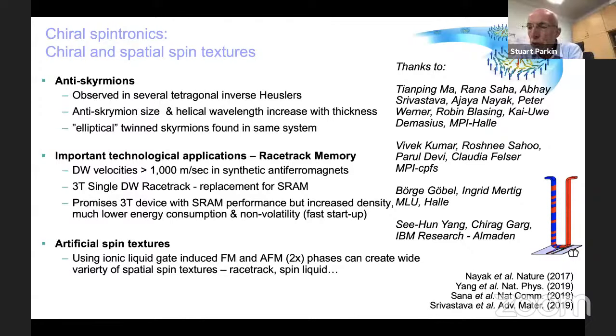Centrosymmetric antiferromagnets. Because you spoke of lower symmetry systems. Yeah, that's an interesting question. So let's say you take a cubic system like manganese-3 iridium. It turns out that actually has a chiral structure, a chiral antiferromagnetic structure, which has been observed even in relatively thin films by neutron scattering. And that chiral structure then, so just because it's cubic doesn't mean you can't have a chiral structure, but in that case, it can be clockwise or it can be anti-clockwise.